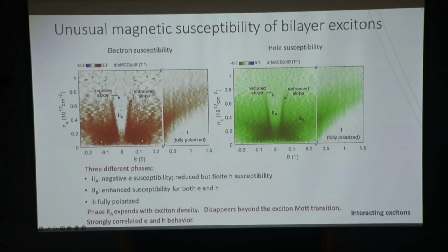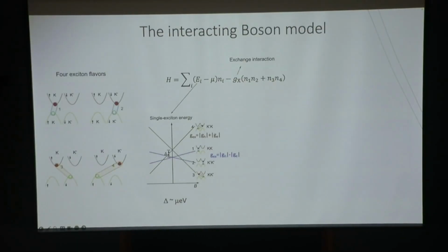Also, you can see the phase boundaries for electrons and holes are perfectly matched. So they have very strongly correlated electron and hole behavior. This tells us these are really exciton behaviors, not separated electron and hole having some strange physics. And the exciton-exciton interactions are very important. We can understand this rather complicated behavior using a relatively simple interacting boson model. This is basically the Hamiltonian: you just have the behavior of individual exciton species plus an interaction mediated by exchange between intravalley excitons or intervalley excitons.